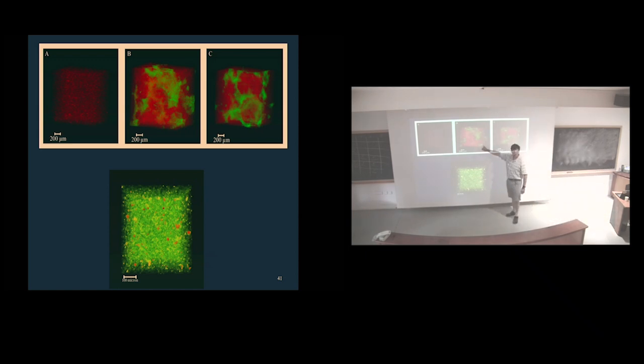The only problem is we also got with that system microcracks. We're trying to solve this problem. We want the correct polymorphic form, but we find cracks. That green stuff is little cracks. And this is 200 microns here, so you can imagine you have little cracks in the chocolate, which then propagate to a visual appearance of whiteness and a weakening of the material sometimes.